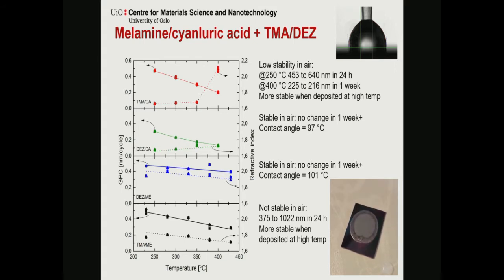And you get this bubbling, so it has a really vigorous reaction in here. So obviously you have unreacted something, or you have really highly reactive aluminium in there. So what could it actually be? Whereas the diethyl zinc version, they were stable in there. You could measure nice contact angles. It didn't happen, so those are actually dead stable.